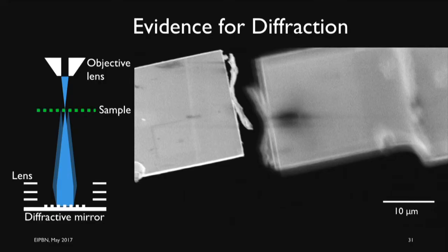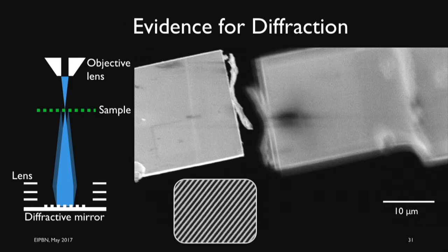This is what would happen. This is an actual experiment. The cantilever on the left is the top surface, and the image on the right is produced when the reflected image is also diffracted. So we have multiple focused beams on the bottom surface, and this is the kind of image that we would see. And you see it's very similar to what we would expect. We have a central brighter image surrounded by, in this case, two other little fainter images with some displacement. Now let's take a look at the orientation of the diffraction grating.